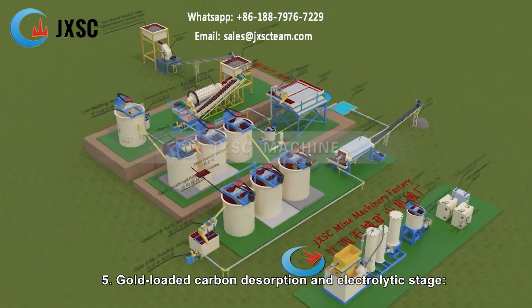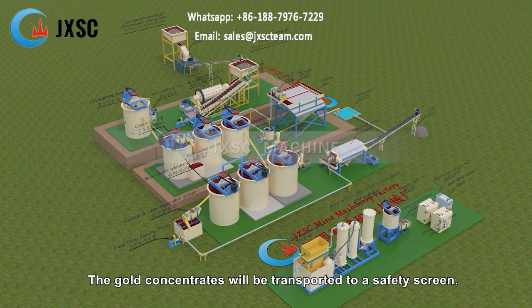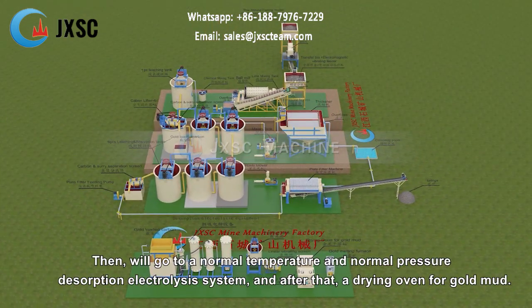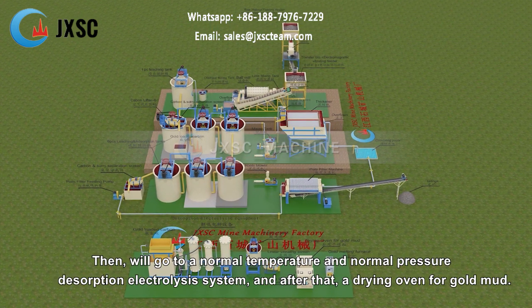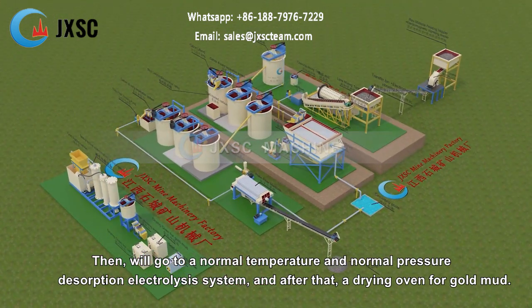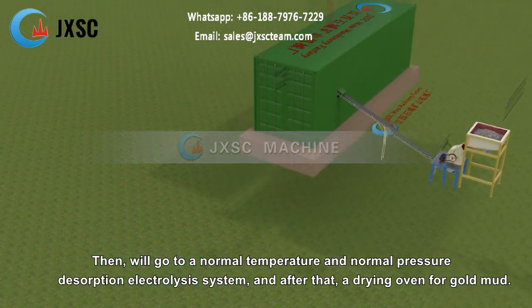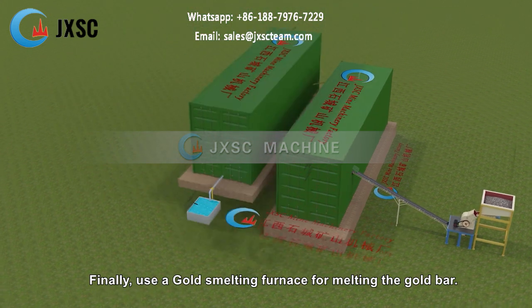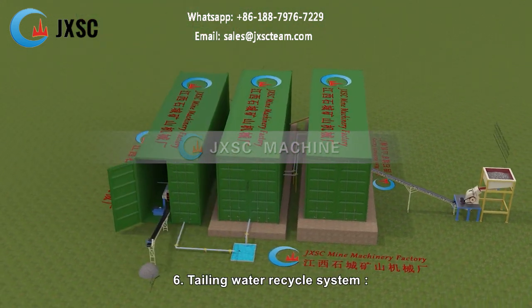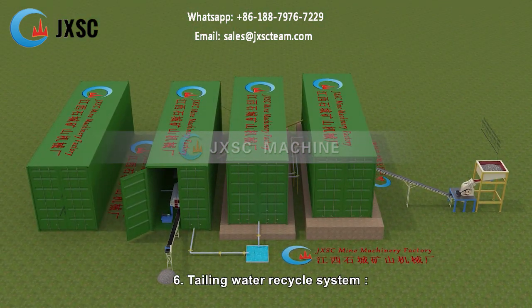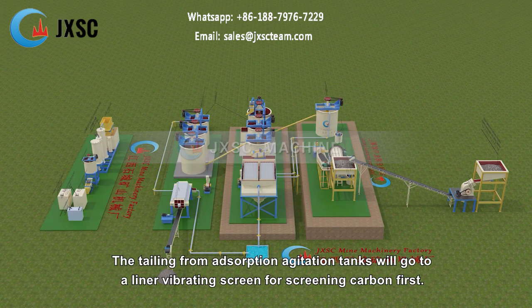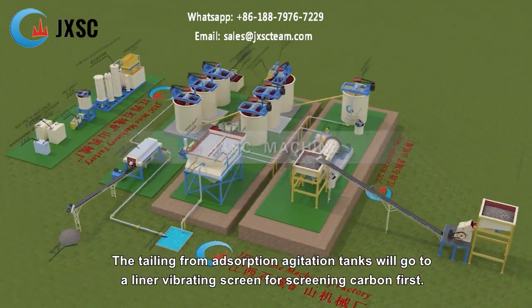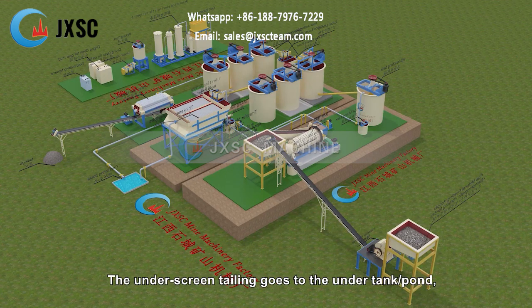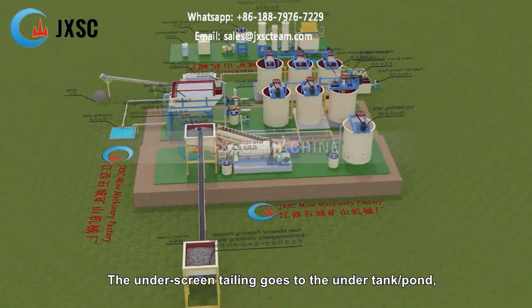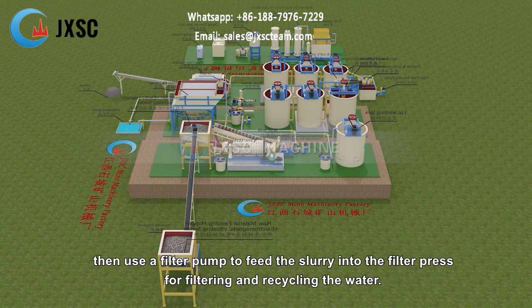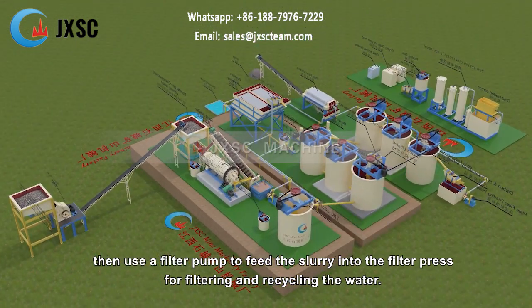5. Gold-loaded carbon desorption and electrolytic stage. The gold concentrates will be transported to a safety screen. Then will go to a normal temperature and normal pressure desorption electrolysis system, and after that, a drying oven for gold mud. Finally, use a gold smelting furnace for melting the gold bar. 6. Tailing water recycle system. The tailing from adsorption agitation tanks will go to a liner vibrating screen for screening carbon first. The underscreen tailing goes to the undertank/pond, then use a filter pump to feed the slurry into the filter press for filtering and recycling the water.